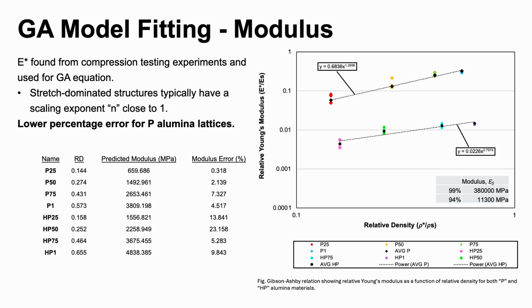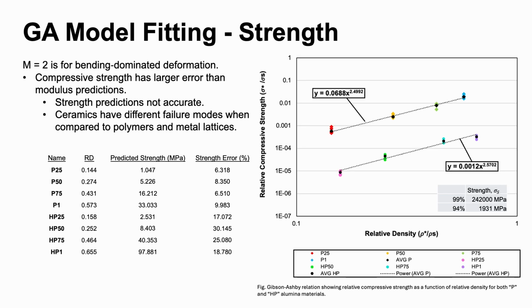We plotted the relative modulus as a function of relative density on a log scale plot, then found the equations to the curves for 94% alumina, which would be the top curve, and 99% alumina, which would be the bottom curve. We found that the constant was the value before x, and the exponent was the exponent following x. When I did the calculations for predicting the modulus, we got a relatively low percent error for 94% alumina when compared to 99% alumina. So then we followed the same procedure for fitting the compressive stress data.